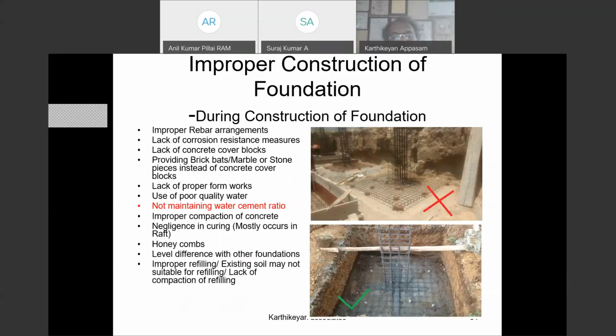And improper construction practice, not maintaining proper water cement ratio, is a very big challenge in most of the constructions. We design M25 or M30 or even M40, but people are still struggling to achieve M20, because there is no proper water cement ratio maintenance at site.